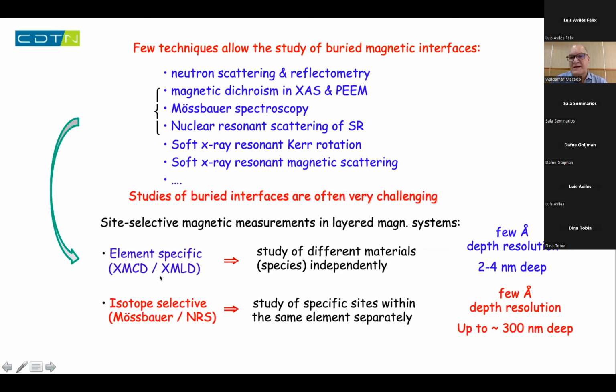XMCD, or X-ray absorption, where you have element specificity. You can select different materials, but the depth resolution is not that great. We cannot go below, let's say, 4 nanometers deep. And the other way to access the information in a selective way is doing isotope-selective measurements like Mössbauer spectroscopy or nuclear resonance scattering of synchrotron radiation, where you can study specific sites within the same material, same element, and with resolution of a few angstroms, you can go up to, let's say, 300 nanometers deep inside the materials. And this will be the focus of part of my talk today.